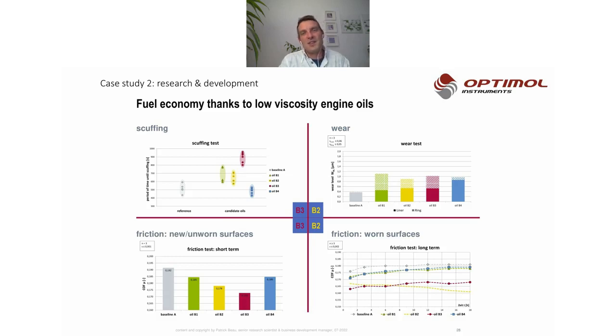So if you sorted out that maybe those 4 candidates are good to go, you would like to have some information on where wear occurs, and that's presented on the right side. As you can see here, the higher the bars, the more wear will occur. On the left side, it's the baseline, the reference. And as you can see, all candidates end up with more wear, because the system is not so suitable for this engine application.